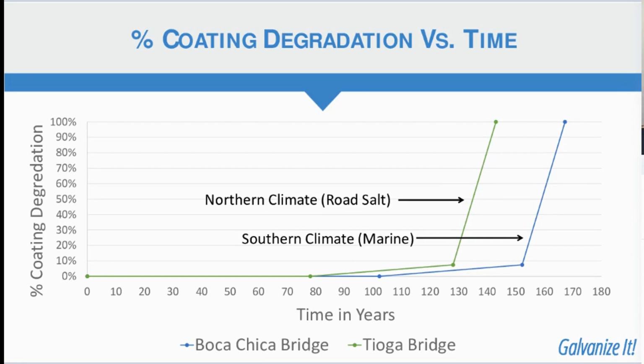Once the zinc coating has completely corroded, then the steel beneath becomes exposed to those chloride ions, where significant corrosion of the steel is not predicted to occur until over 130 or 150 years into the service life of each respective bridge. This high threshold for corrosion to begin on galvanized coatings in the concrete is the primary reason why we say 100-year service life can be achieved with hot-dip galvanized rebar.